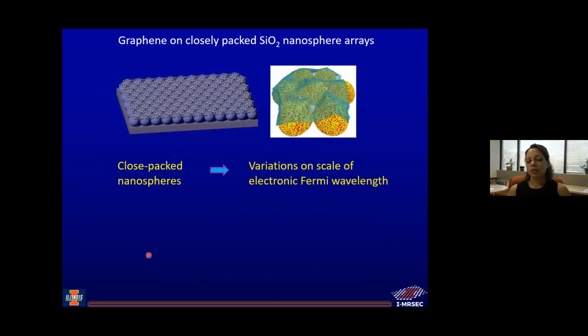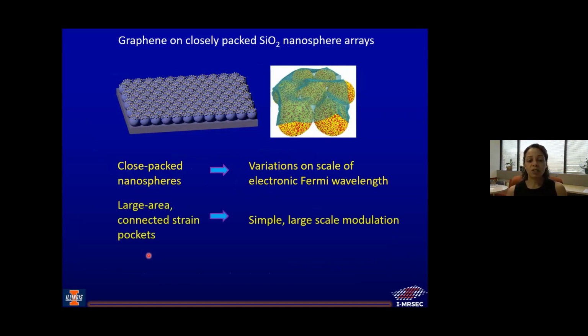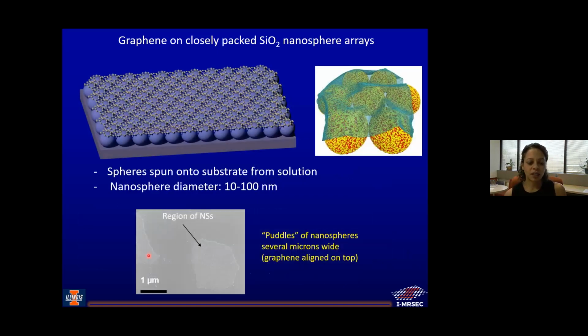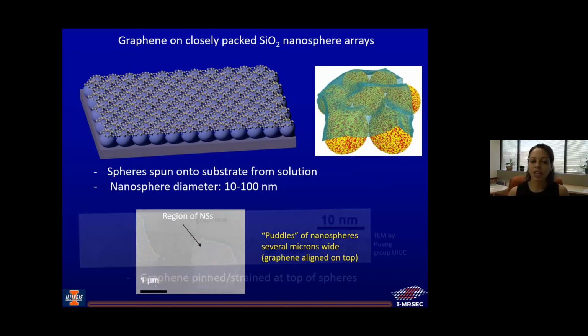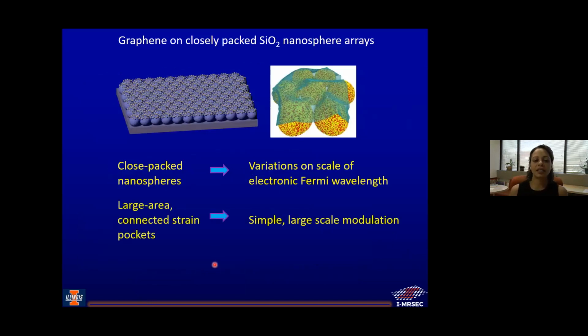Okay, so we end up using these close packed nanosphere arrays. There are variations on the scale of the electronic Fermi wavelength. Like I said, if we want to see changes in conductance, we can do that with length scales from 10 to hundreds of nanometers, exactly the sweet spot that we wanted. We can do this over large areas. If you look back over at this picture here, we can get regions of nanospheres that are many microns long or more. Here we weren't trying that hard to get a uniform array across a chip, but you can do that if you want to. So you can get large area connected strain pockets that can be easily and simply modified. And you also get a very small radius of curvature if you have 10, 20 nanometer nanospheres, which give you large strain gradients.